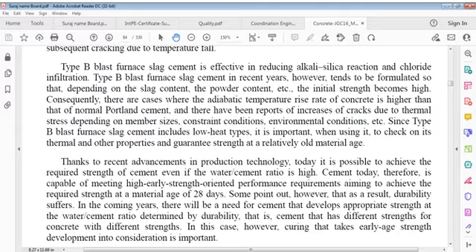Helmuth suggested. According to them, rapid initial rate of hydration at high temperature retards subsequent hydration and produces a non-uniform distribution of products of hydration within paste.